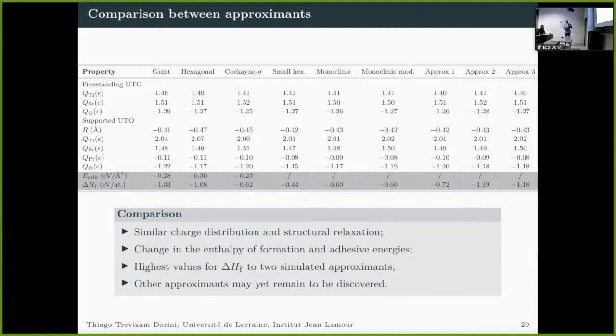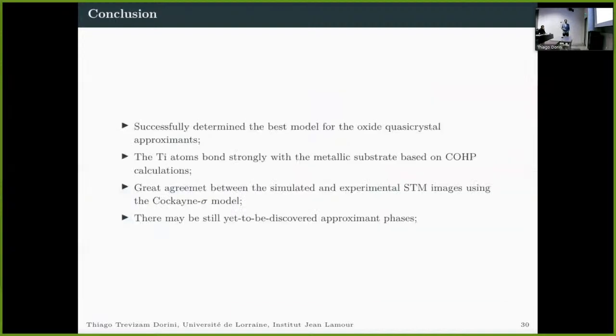And the enthalpy of formation also varies considerably depending on the composition. We can see that the two manually discovered approximants, approximant 2 and approximant 3, have the lowest enthalpy of formation, even lower than two of the previously discovered approximants, the giant and the hexagonal, which leads us to believe that there may still be many other approximant phases yet to be discovered.